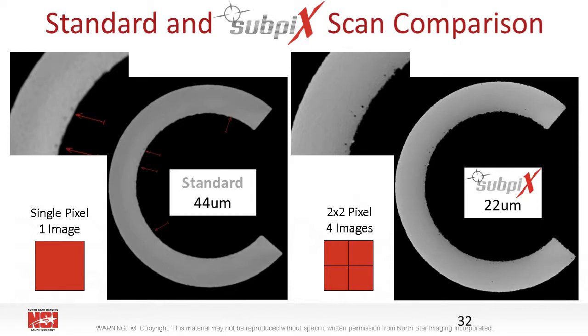Here's another example of a standard and subpix scan comparison. This sample is an additive manufactured part. On the left-hand side, we generated a technique that provided a 44 micron voxel size, and you can just start to begin to see the porosity showing up next to the red arrows. On the right-hand side, we generated a subpix technique. All other processing variables, again, the same, except for the movement of the detector, creating 4 images in a subpix mode. And we ended up with a 22 micron voxel size. And you can clearly see the porosity showing up now.